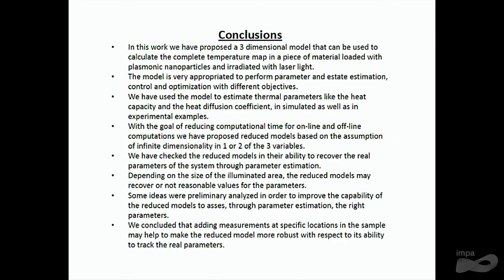Well, finally, I would like to put some conclusions. We have proposed a three-dimensional model that can be used to calculate the complete temperature map in a piece of material loaded with plasmonic nanoparticles and irradiated with laser light. The model is very appropriate to perform parameter and state estimation, control and optimization, something that we will try to do in the future. We have used the model to estimate thermal parameters, like the heat capacity and the heat diffusion coefficient, in simulated as well as in experimental examples, the ones I showed you in the last slides.